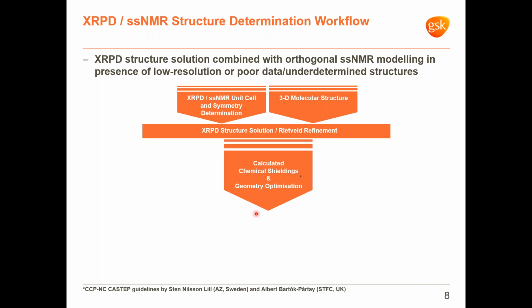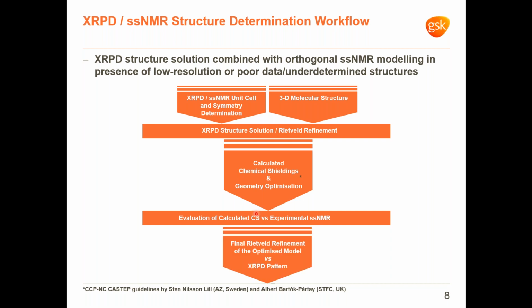But this is where solid-state NMR can really help. The CASTEP package can be used to calculate chemical shieldings from the most likely structural models. The chemical shieldings can then be converted into chemical shifts and assessed against the experimental solid-state NMR spectrum of the target structure. And the assessment is then repeated after a geometry optimization, which should improve the agreement with solid-state NMR data. And at this point, we should be more confident in the selection of the structural model to progress to the final refinement step.